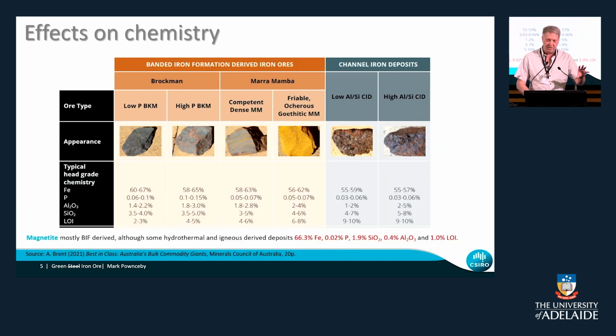And with all these alteration processes that have happened to the iron ores over time, there's a significant effect on chemistry. And I think Gus showed this slide yesterday, but it's worth repeating that there are different types of iron ores out there. So the original high-grade iron ores discovered in the 50s, at Mount Whaleback and Mount Tom Price, were probably these Brockman ores, these really high-grade, 60 to 67% iron, really low impurities. But as I said, over time we've had lots of alteration. We've gone from these really hematite, Brockman type ores to these Marra Mamba type ores, which are goethite, hematite, martite dominated.